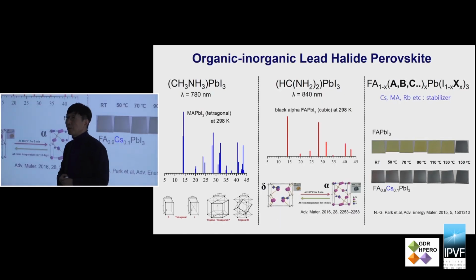And we have two important compositions. One is methylammonium lead iodide, and the second one is formamidinium lead iodide. Probably formamidinium lead iodide is better than methylammonium lead iodide because of the narrow band gap, meaning that you can utilize long wavelengths of light. However, methylammonium lead iodide has a pretty stable perovskite phase, even at ambient conditions, room temperature. However, formamidinium lead iodide is not stable at room temperature. It tends to undergo a phase transition from the perovskite alpha phase, which is the photovoltaic material, to the non-perovskite delta phase, which is not a photovoltaic material.